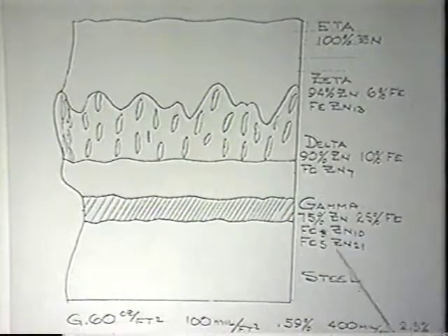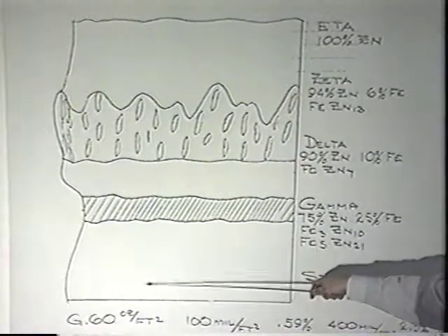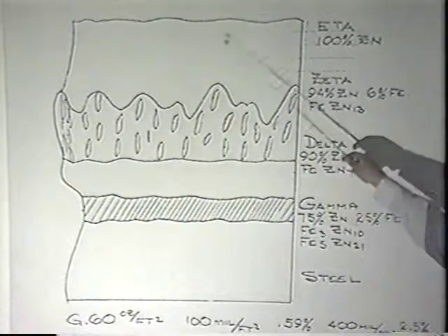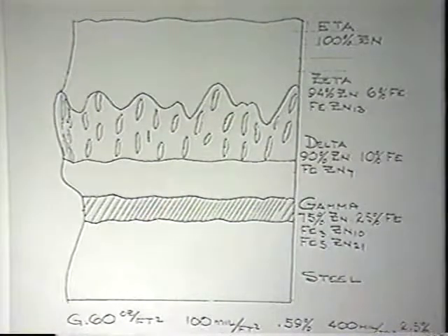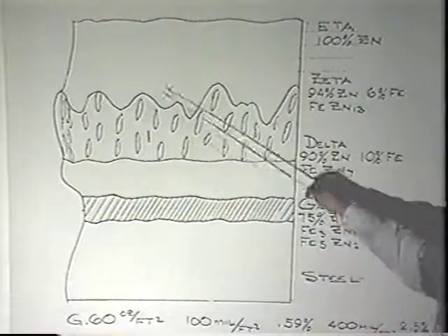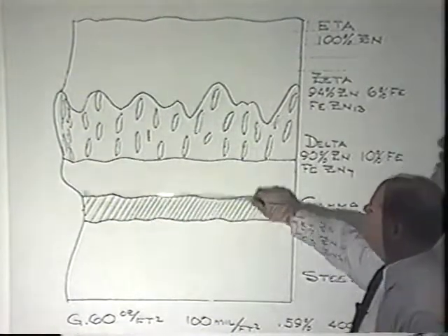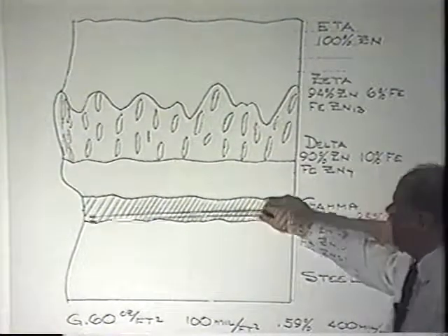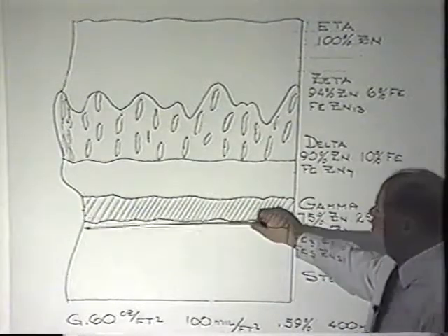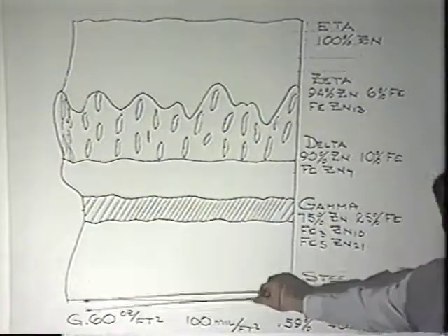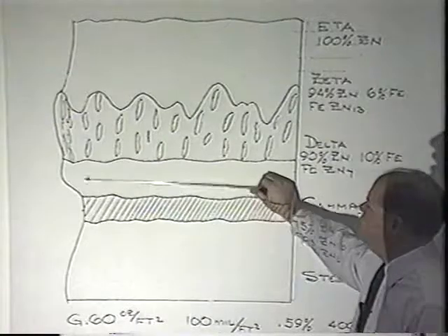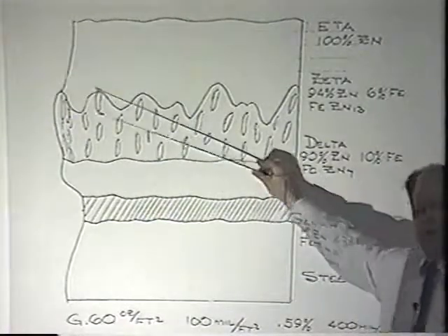Okay, the coating itself, here would be your steel coming down here. When it goes through the hot dip line, our steel is heated up to about 860 degrees because it's coming out of an annealing furnace, and we'll show you that when we go through the line. But the steel is about 860 degrees. The molten zinc is about 860 degrees. So you've got a fair amount of heat there. From here on out is where the zinc's going to hit the steel. And when the zinc is applied to the steel, the iron in the steel will actually start to migrate up through the coating, forming an alloy layer there.